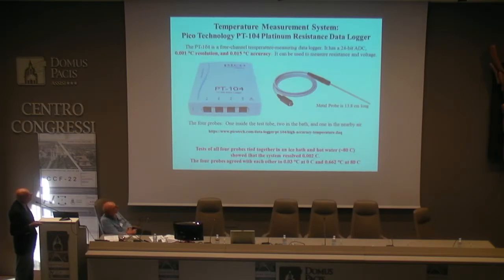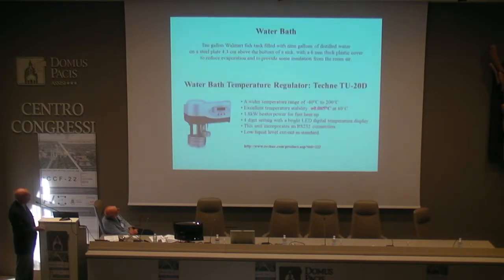The temperature measurement setup is shown here. It's a 4-channel commercial system with milli-degree resolution and about a 100th of a degree accuracy, supposedly. We've checked it in an ice bath, so it looks not quite that good, but good enough for the experiment. The water bath, we have a temperature controller. It's nominally good to about 5 millidegrees, but it actually doesn't work that well. But again, it should be good enough.